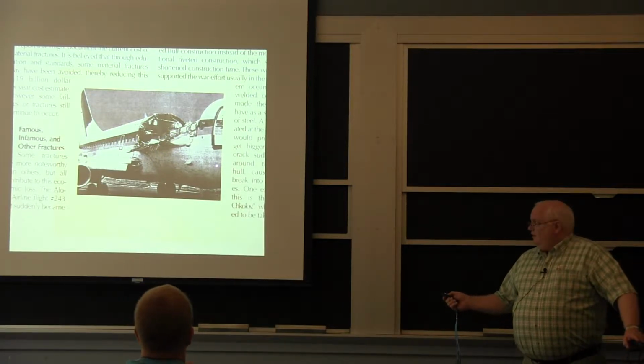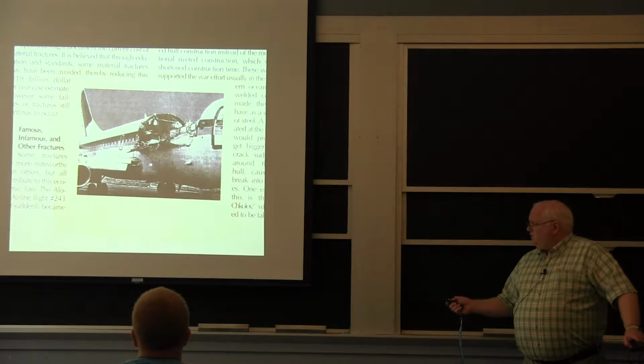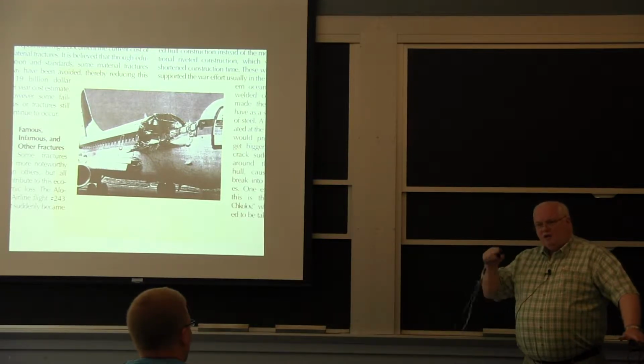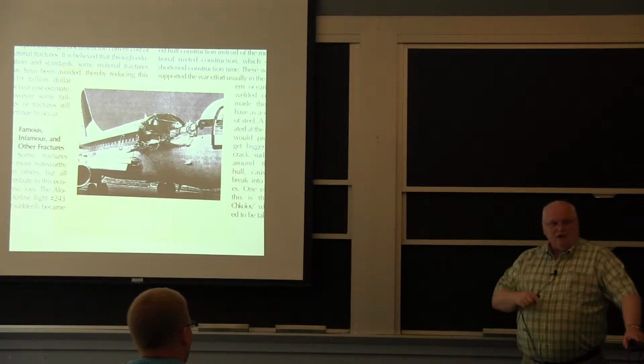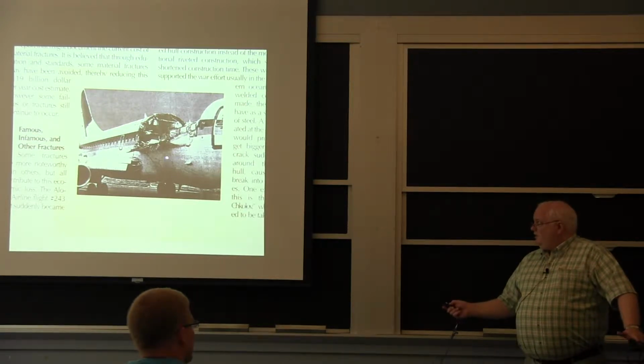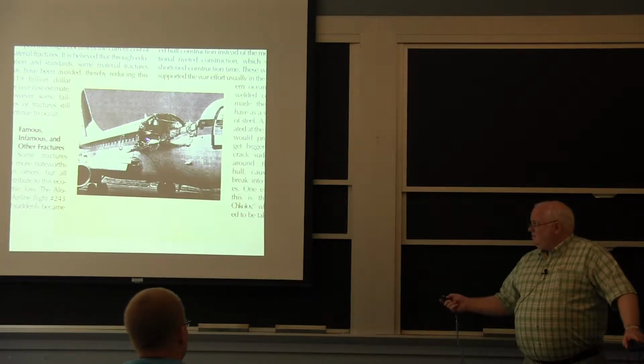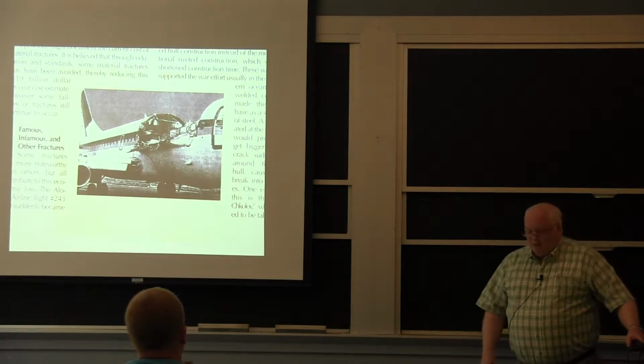Anybody know what this is a picture of? Aloha Airlines, okay. This was 25 years ago now. It was a while ago. But this was, I think, a 737. And it was basically flying on scheduled flights between islands in Hawaii. Except for being flown out to Hawaii, it was always just doing these 20-minute flights from island to island, okay? And so as a result, it had like 100,000 cycles or 60,000 cycles in about half the time of a regular aircraft, because its flights were an average of 20 or 30 minutes as opposed to 45 minutes or an hour, because the islands are so close together.